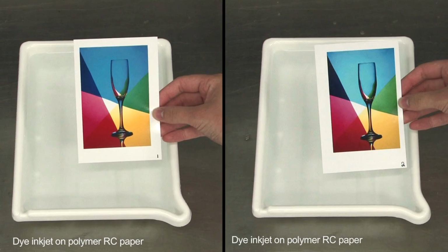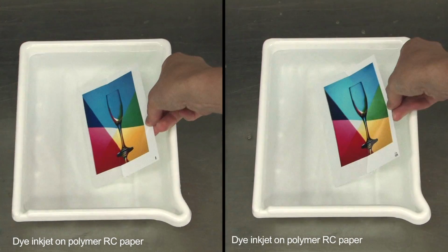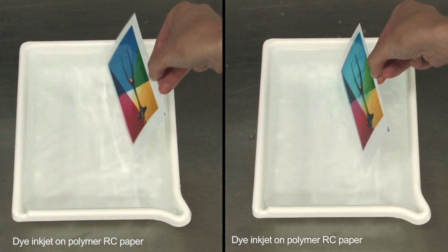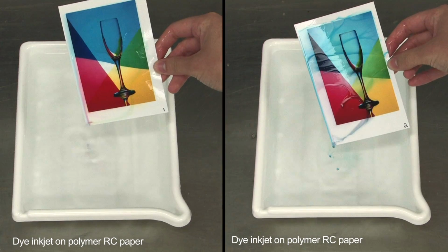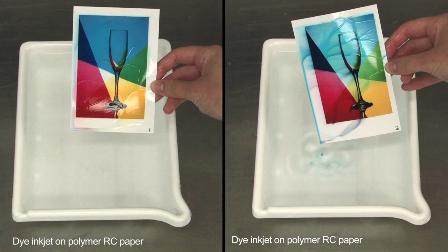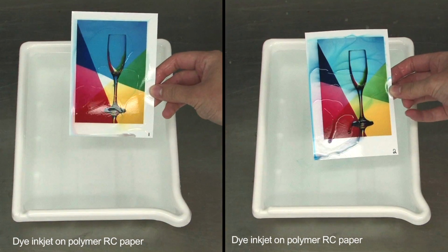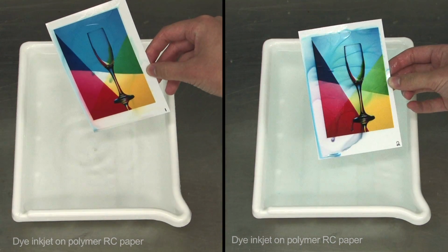Samples 1 and 2 are both dye inkjet on polymer-coated papers. Both prints bleed immediately on contact with water. The surface of the print on the right also appears to melt as the polymer coating dissolves away with the ink.